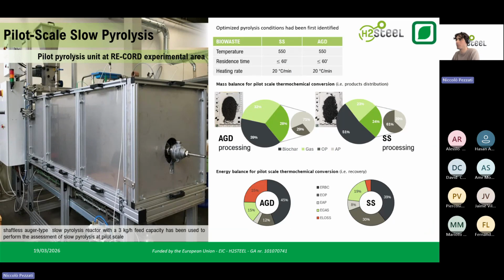So the first stage of this integrated process is the slow pyrolysis that we carried out at a pilot scale here at Record, for which we have first optimized the conversion conditions at a laboratory scale, and afterwards we have replicated those in the pilot unit. So the parameters that we have focused on are temperature, the residence time, and the heating rate of the conversion chamber.